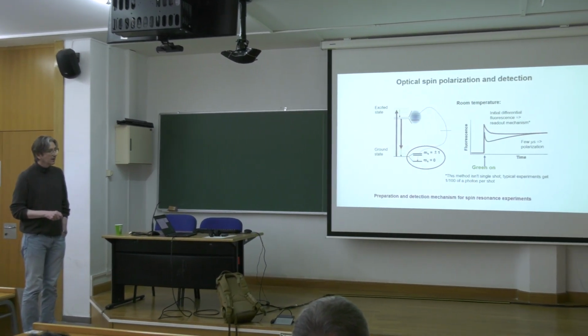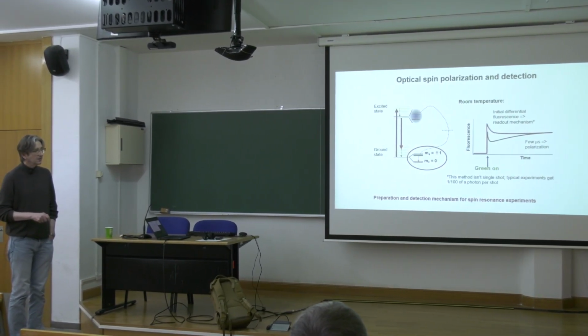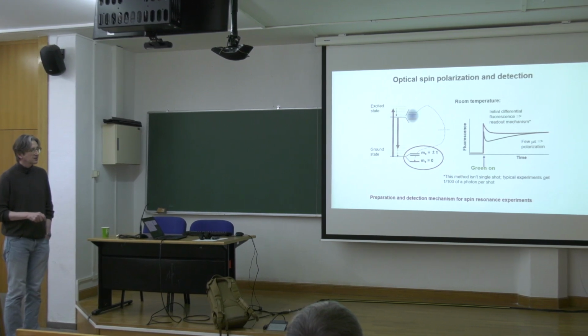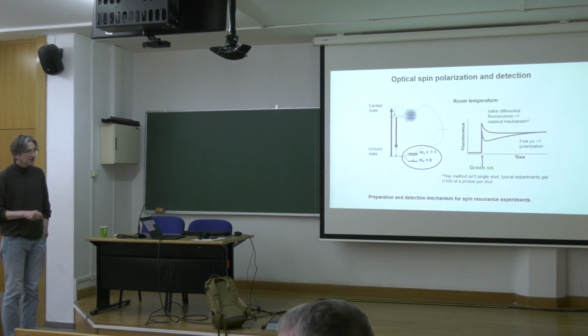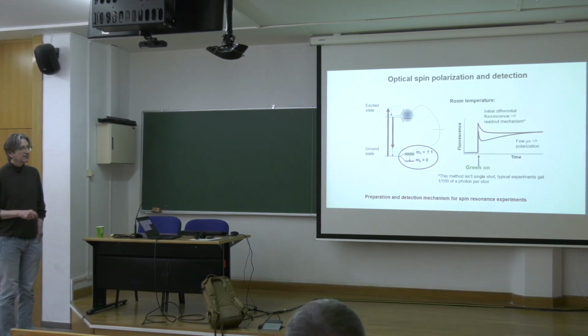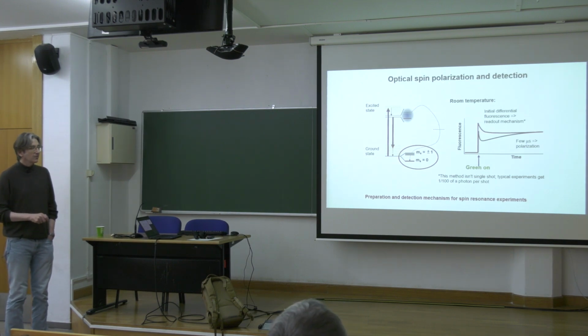into one particular sublevel of the triplet state spin manifold, the so-called magnetic spin quantum number 0. This magnetic quantum number 0 substate fluoresces stronger if you excite it with a laser compared to the 2 other sublevels. And by measuring fluorescence intensity, you can distinguish between the ms equals 0 spin state and the 2 others. These plus and minus 1 spin states have a lower fluorescence intensity compared to the ms equals 0 spin state.